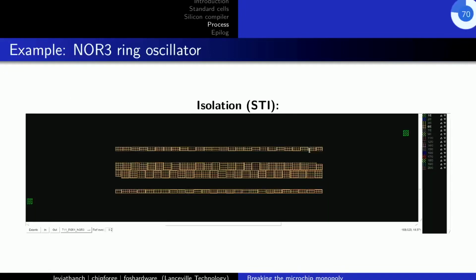It's really simple. After you get your wells out of the furnace, so I did a little detour, you want to make sure that the lateral diodes, which came into existence after diffusion, don't create unwanted short circuits. So we use a technology actually developed much later, after 1 micron had already been out. It's called STI, shallow trench isolation. It's from the ULSI technology, as well as the silicide we use to reduce the resistance of the polysilicon gates.